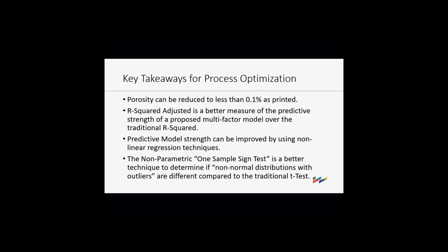Okay. We were able to get less than 0.1%. Actually, they can't measure the porosity on our products now. So we have made a decision for implants, we'll still HIP, just because the FDA likes it. But for instruments, we don't have to HIP. So we made a really nice breakthrough to get to 0.1% and less than that.